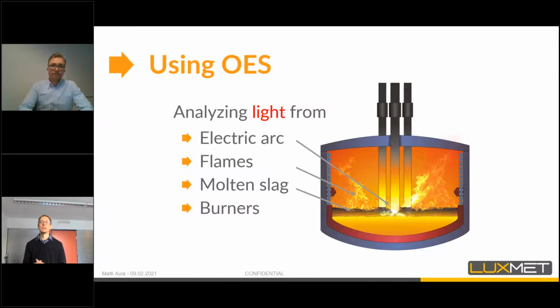So I was discussing earlier these different types of spectrum. Many people ask what the relevance to the process actually is. When we talk about the light coming from the furnace, it's actually quite important to know what we are actually seeing. Because oftentimes, for example, if your off-gas temperature rises, it can be for many reasons. But the biggest thing to separate in the data is whether it is coming from the flames or from the slag surface. Because we never want to mix up flame temperature with the actual melting of the slag. So in this way, with the spectrum analysis, we can filter the data to contain only the information we need in process control, and we don't make false assumptions of melting or some kind of combustion reaction occurring in the furnace.